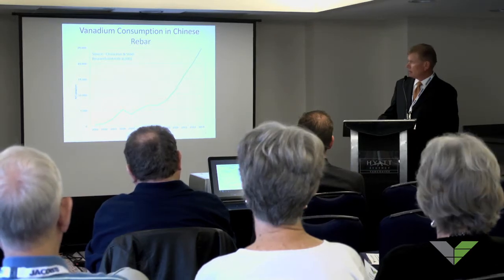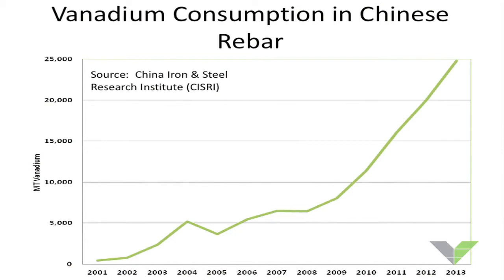So in 2004, really overnight, this new market developed, and we saw this surge in demand coming from China. And what happened is the price reacted. The market got overrun. China's always been an exporter of vanadium, and suddenly they became a net importer. And if you go back and look at the price history, you'll see the 2004 price spike where prices shot up to a ridiculous level. And when vanadium got to $130 a kilo, it just becomes economically unviable for people to use. And so what you saw is when prices reached ridiculous levels, we saw some substitution here. And this is people basically using substitutes for vanadium to make that grade 3 rebar, specifically in this case moving to niobium plus titanium rather than vanadium.